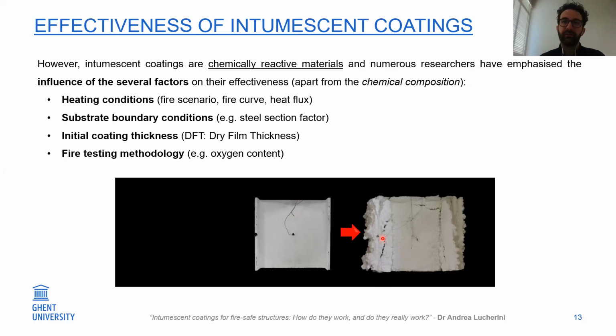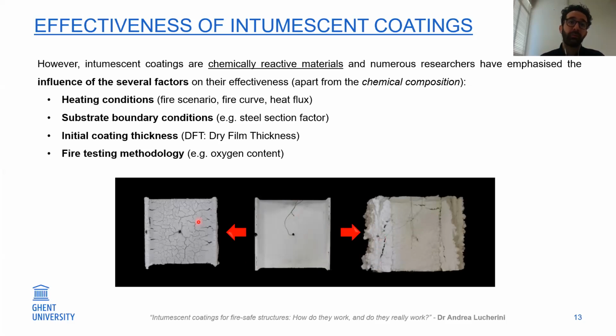Instead, I also exposed the same coating to a different time curve of fire. The fire in this case was reaching the same high temperatures, but with a different heating rate. So it was getting there in a slower way. So you can see here that the coating in this case mainly didn't activate properly, and it created this very thin char that actually didn't protect the steel beam properly. And this is a problem.